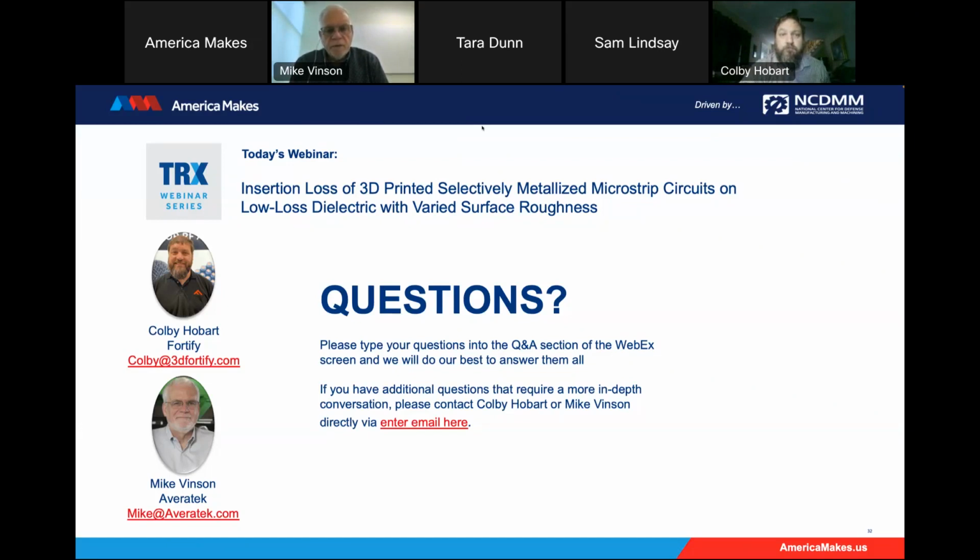But typically we plate up around 30 microns or 1 ounce copper in that range. Half ounce, 1/4 ounce are doable. But we can also do extremely thin metals, such as 100 or 200 nanometers, when those kind of resistances in the metals are sought. Okay, I was just going to ask you about the thin metals. I think a lot of people are very interested in that area today.